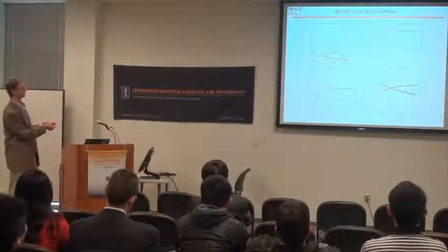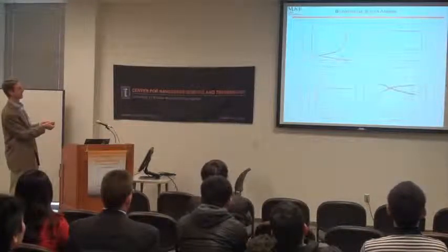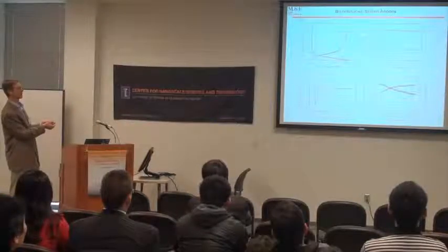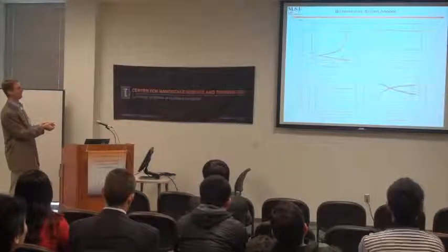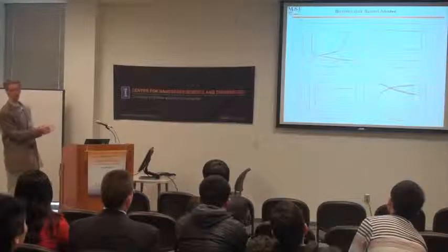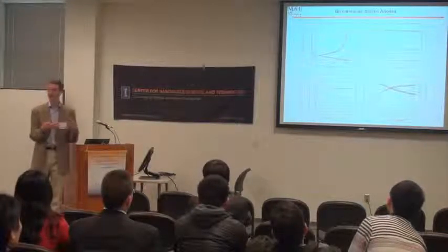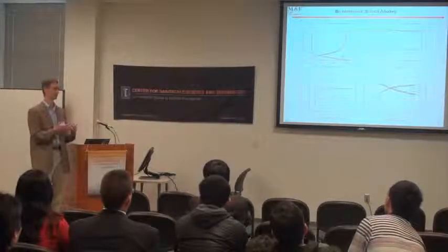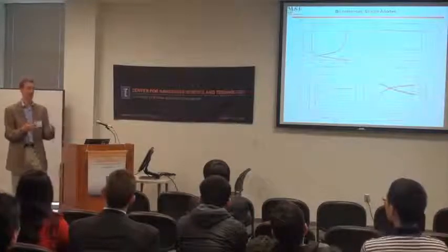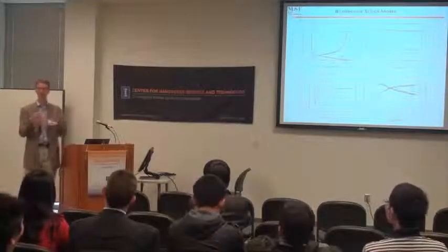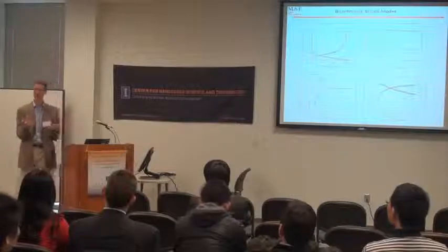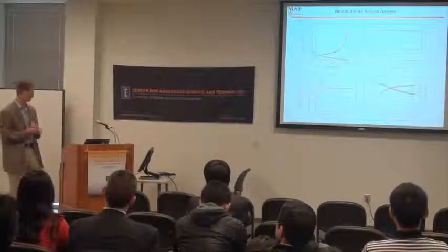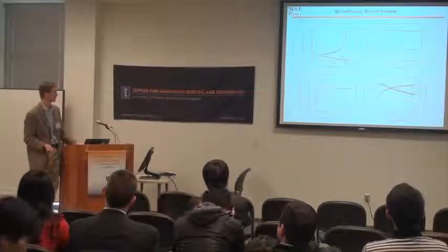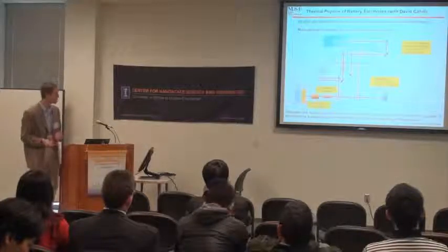But why we're interested is, at least for 30 cycles, we have capacities here which are on the order of 3,000 milliamp hour per gram. If you compare that with carbon, which is about 300 milliamp hour per gram. So there really is the potential here, I think, to, again, increase the energy. And it is also by using these sort of properly designed three-dimensional scaffolds to provide the characteristic properties you need.